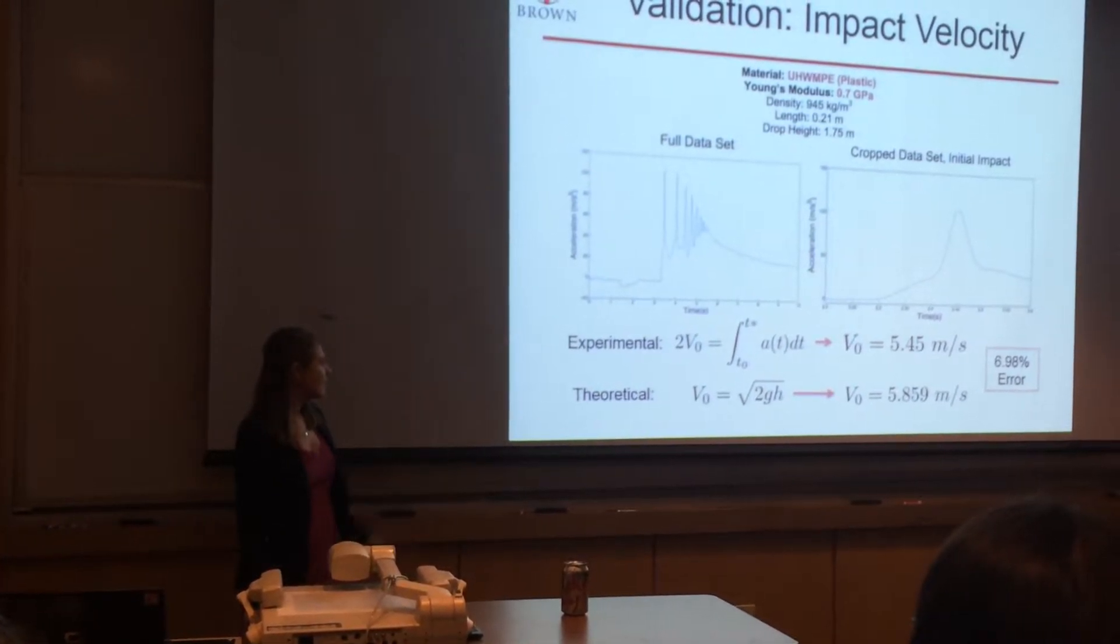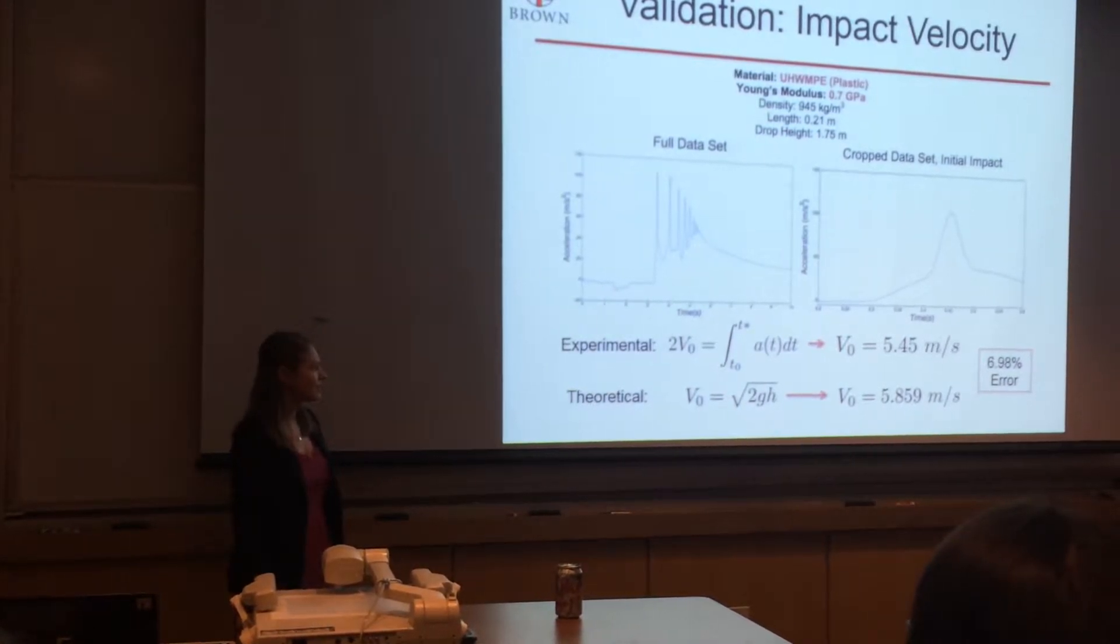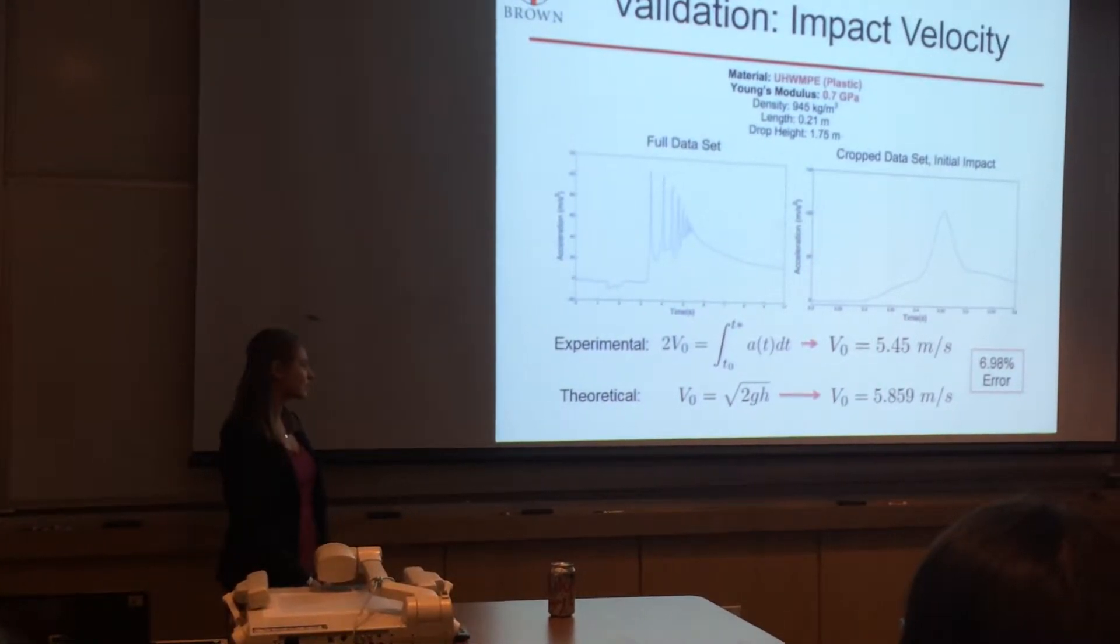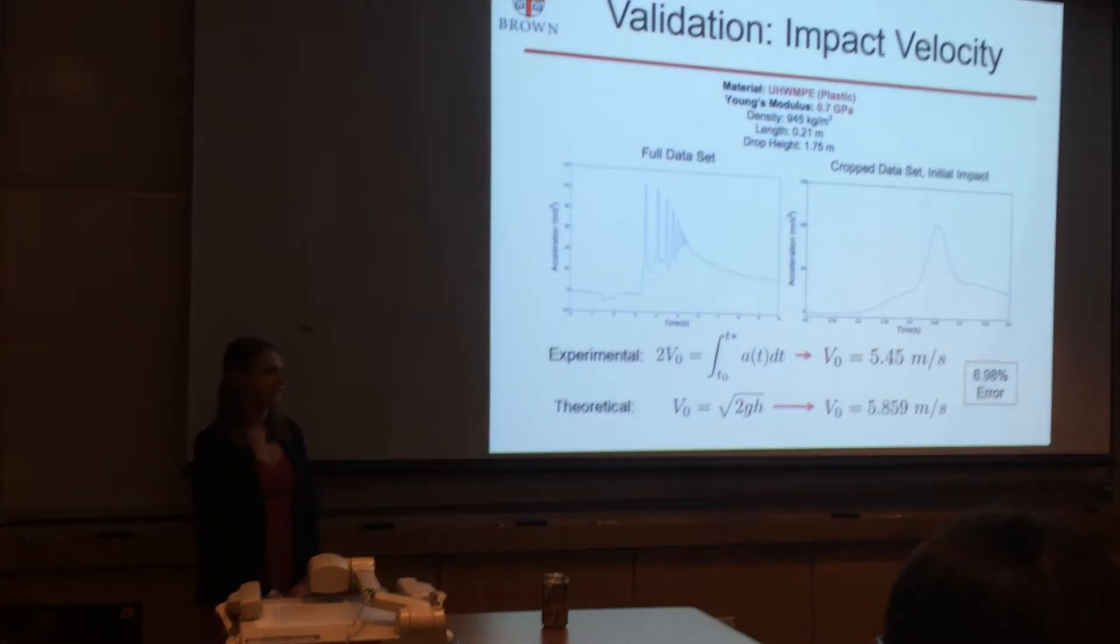I got the experimental impact velocity using this curve to be 5.45 meters per second compared to the theoretical 5.859 meters per second. Thus I had only a 7% error.